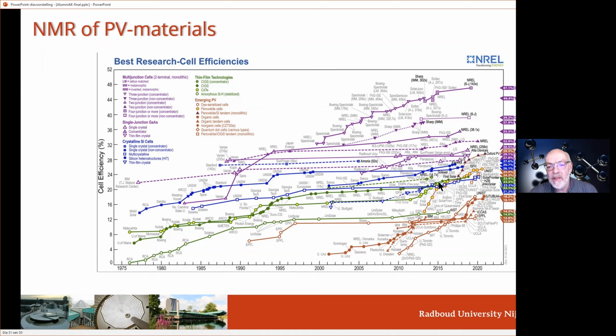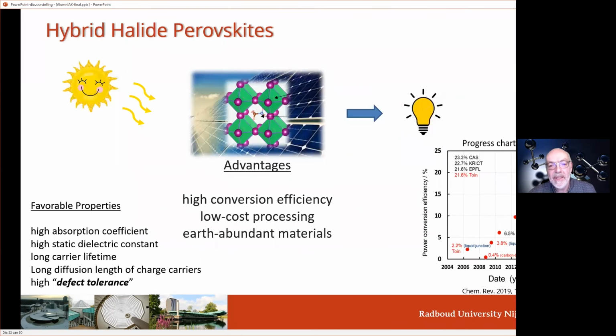And they went from an efficiency of a few percent to an efficiency that already outperforms polycrystalline silicon cells. And this happened in a decade, whereas these silicon cells were developed for 50 years and they are above 20% now. And the base structure of these materials is methyl ammonium lead iodide. It can be made to have a super high energy conversion efficiency. It can be processed at ambient temperatures. So silicon, you need to process at high temperatures, what have you. These materials you can simply make by mixing methyl ammonium iodide and lead iodide. You mix it and you have the perovskite. And all these elements are earth abundant.